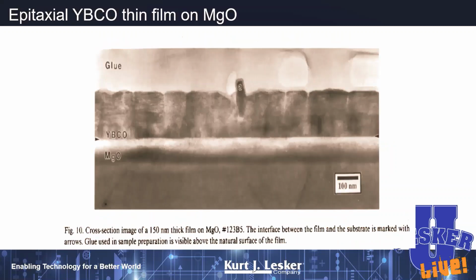And in that case, we would use things like single crystal magnesium oxide substrates, which were lattice matched to the yttrium barium copper oxide films that we were depositing. And with that lattice matching, we grew these beautiful c-axis oriented films. In a polycrystalline film that's not oriented, we would get critical current densities of maybe 100 amps per square centimeter of cross section. If we could grow beautiful c-axis oriented films, we had current densities which were 10 million amps per square centimeter of cross section.